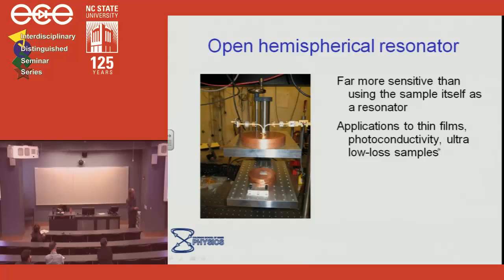And we inject the transmitted field here, and the field that comes out of the cavity comes here, okay? By selecting the distance between the mirrors, we can select the mode spacing in the cavity. Our preliminary estimates are that the cavity has a Q of about 500,000. That means that if a wave or a photon goes in, it bounces around roughly 500,000 times before it leaks out. So that gives you an extremely sensitive measure.